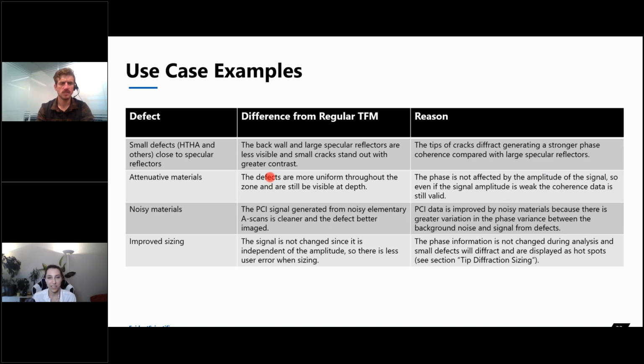It improves sizing, as I mentioned a little bit earlier. The signal is not changed since it's independent from amplitude, so there's less user error in that sizing. When the phase information is not changed during analysis, and the same defects will diffract in the same way and are displayed as hot spots, we can really see the diffraction from those cracks, for example, and we'll look at that in the tip diffraction sizing technique section.